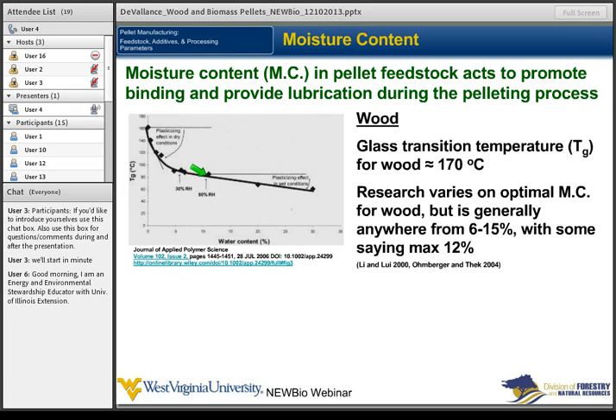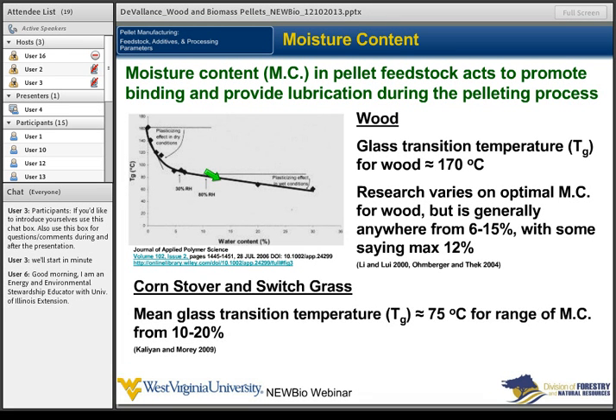If we're looking at what moisture content we should be at, I've seen various things. In terms of the optimal one, anywhere from 6 to 15 has been shown in the literature. Other people say 12 is the max moisture content you should have. I've seen 8 to 12, but a lot of times when I'm doing my work, I try to stay up towards 12 and lower the die temperature that I need to be at. If we're looking at corn stover or switchgrass, they have a glass transition temperature of about 75 degrees C when we're at a moisture content from 10 to 20.